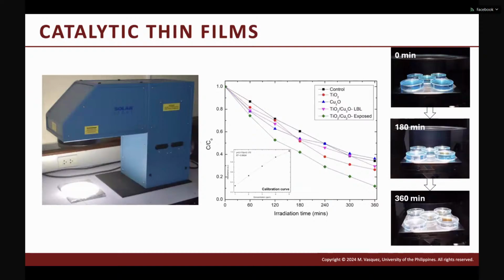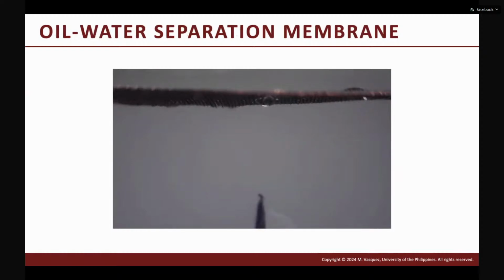We also have catalytic thin films. We actually use this for wastewater degradation. So these are titanium dioxide-based catalysts, and we use this to degrade organic matter in aqueous solutions. This one is an oil-water separation membrane. So we deposit different materials on the mesh and use this to separate oil and water. The good thing about this material also is that it has self-cleaning properties. So if we expose this to white light, then we can remove any residual oil on the mesh.